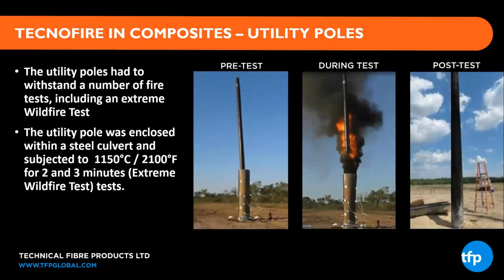The poles had to pass a number of fire tests, including the extreme wildfire test, where the pole is enclosed in a steel culvert and a significant fire is established, reaching, as I mentioned, 2,100 degrees Fahrenheit, as seen in the photos. And I think these really highlight the severity of the test and how challenging it is for composites to successfully pass this test. And you can just see in the middle photo, there's a wire attached to the top of the pole. The pole is actually under flexural load during the test to assess retention of mechanical properties during and after the fire.